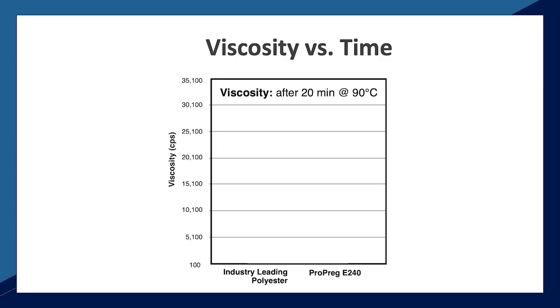The ProPreg E240 will dispense, flow, and wick into PEEK-coated wire much better than the industry-leading polyester, without dripping, backing out of the slots, or getting on the laminations, inside diameter or outside diameter. The resin will not bond the chuck fixtures. This can be attributed to the difference in surface tension due to the lack of solvents or acrylate monomer in the E240. Here you will see the viscosity after 20 minutes at 90C.